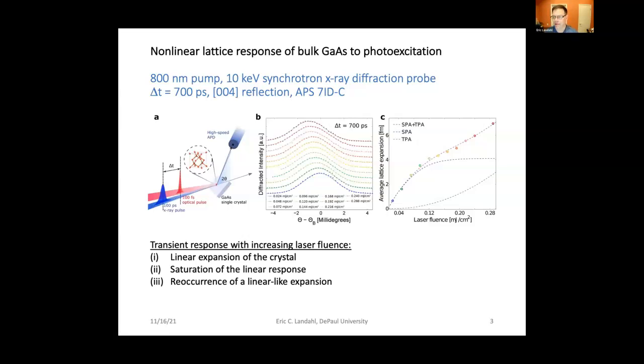This data is from the 7ID beamline at the Advanced Photon Source. So it's a 10 kilovolt synchrotron X-ray pulse, 100 picoseconds in duration, with an adjustable time delay from a 100 femtosecond Ti-Sapphire 800 nanometer laser pulse on a perfect crystal of gallium arsenide at room temperature. And it's just a point detector, so we have really great angular resolution with this technique. And that becomes important when you try to view electron behaviors, which would be very fast, with a relatively slow machine that's taking snapshots at 100 picoseconds, as I'll explain.